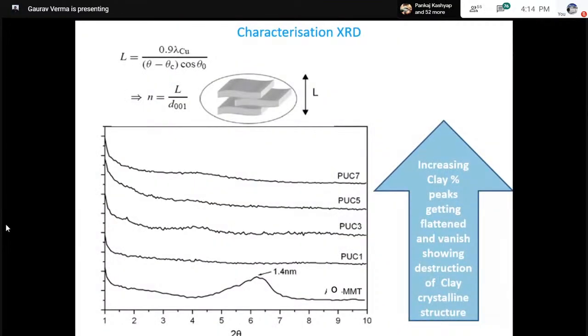How do you actually characterize it, and how would you know that a nanocomposite has been formed? The first kind of characterization technique which you would use is XRD, which is X-ray diffraction, very popularly known. And when you see a destruction of this crystalline structure associated with these clay platelets, you would know that you ended up making a nanocomposite. But a word of caution I want to put here is, do not be misled by the structure or the spectra shown by XRD, because you're using 95% polymer and only 5% nanofiller. Your nanofiller weight is less than 5%. So anyway, you would see the majority of the polymer-like non-crystalline features. And XRD, being a bulk technique, would not give you the real story behind it.